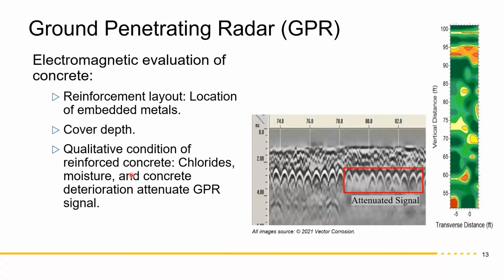Let's take a little bit of time. So here's a test for ground penetrating radar. You go in the column. Bernie mentioned this also. Basically, this is a line of data. These hyperbolic events are reflections from the steel. So the tip is where the rebar is. The time of flight it takes to go back and forth gives you the cover depth, which is very important because if you have areas of low cover, that's probably where the corrosion is happening.